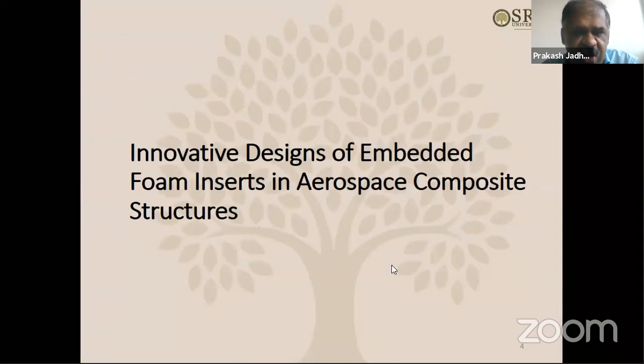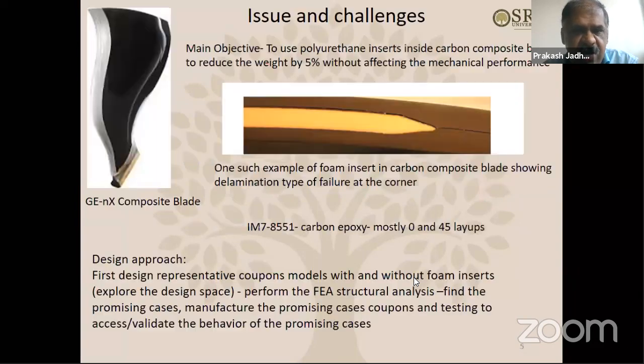So this is what we tried to explore here, the use of these embedded foam inserts. The main objective was to use polyurethane foam inserts inside the carbon composite fan blades to reduce the weight by 5%, but without affecting the mechanical performance. As you can see, there's one example given there. In the image, the yellow is the polymeric foam insert, the polyurethane foam insert, and the black part is all carbon composite. One example was manufactured and tested, and it was found that from the tip of the foam, delamination is occurring and propagating to the end. So basically, this is what was observed.